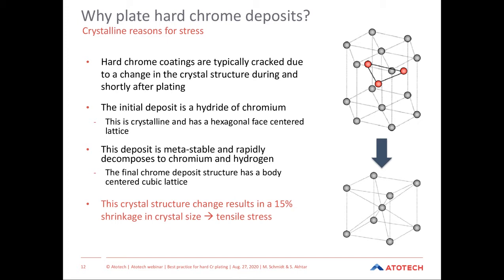So we form a body-centered cubic lattice structure. And this change in the structure has an impact in terms of a shrinkage in the crystal size structure. So we see a 15% shrinkage in the crystal size. And this leads to tensile stresses forming within the coating. And the only way the deposit can overcome these stresses is that it starts to crack.